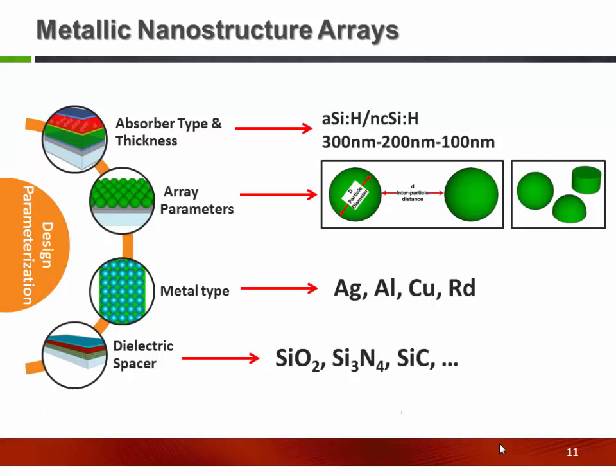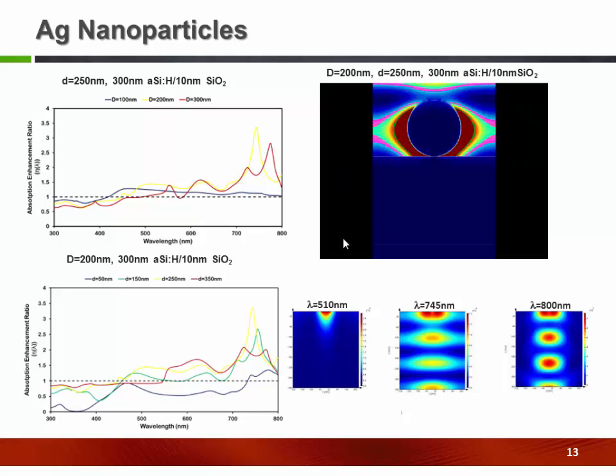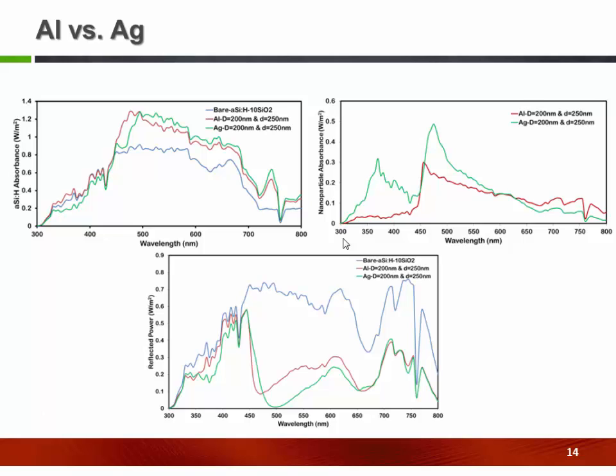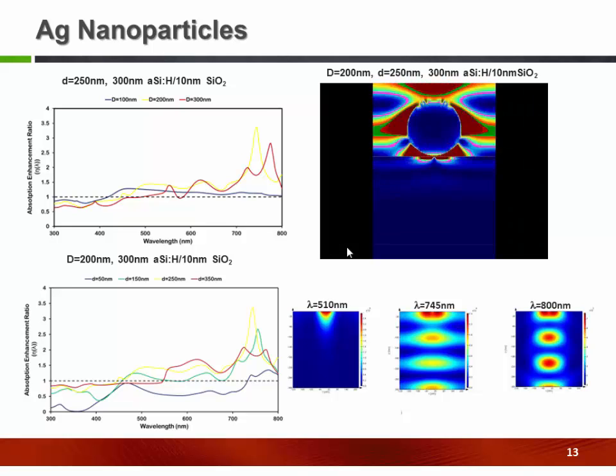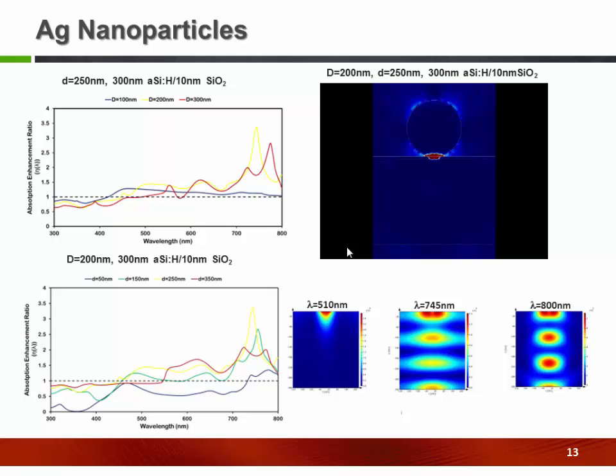Actually, I wasn't sure if I could show you this movie, but I have it. This is the whole phenomenon happening from the incoming light. As you see, the incoming light causes a resonance effect inside the metallic particle. That's the plasmonic resonance. And as you see, exactly this resonance causes a light increase at the interface of the metallic particle with the absorber layer. You see this enhancement due to the resonance.